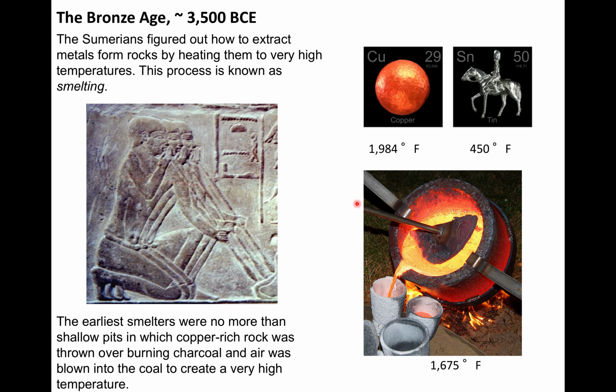So this is a slide I showed several lectures ago, and I talked about the ancient Sumerians who figured out how to extract metals from rocks by heating them to very high temperatures. And we term this process smelting. The most important part of smelting is this, the melting process. And I showed you a video, but here I'll just show you with still images, that what the ancient Sumerians figured out how to do is to take copper, which has a very high melting temperature, add a little bit of tin, which has a very low melting temperature, mix those up, so literally think of mixing them with a mortar and pestle, and then they would put them into a furnace, and then they would blow air with oxygen into that furnace, and by doing that, the copper plus tin mixture would melt at a lower temperature than pure copper melts, and they could pour that into molds, and that produced bronze.